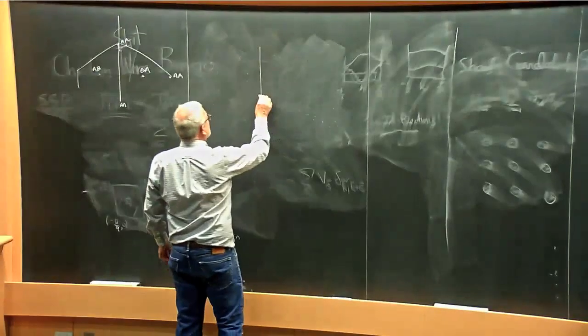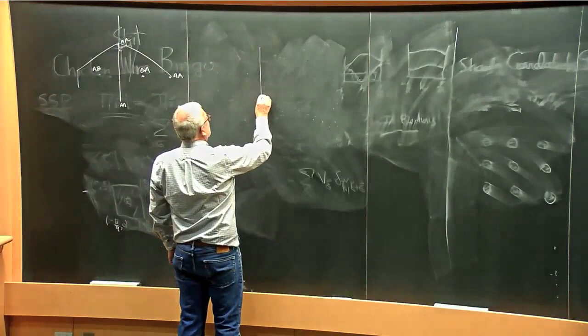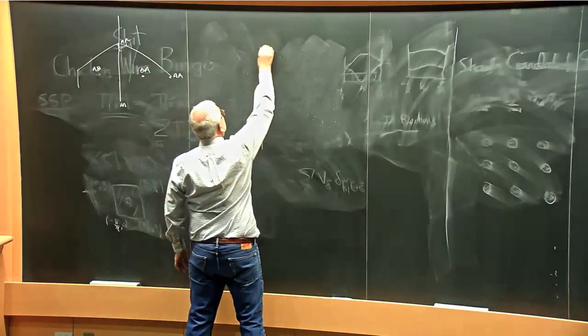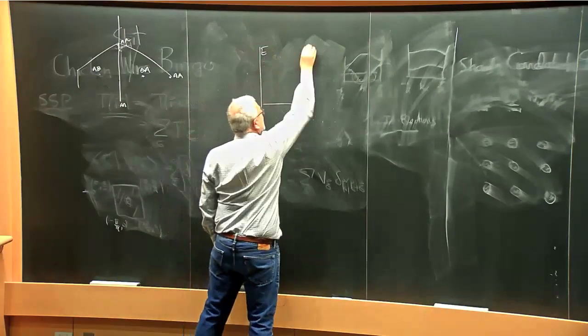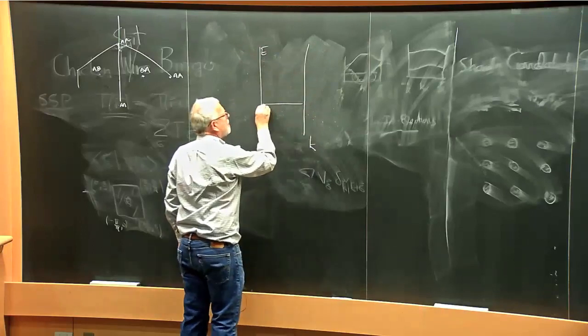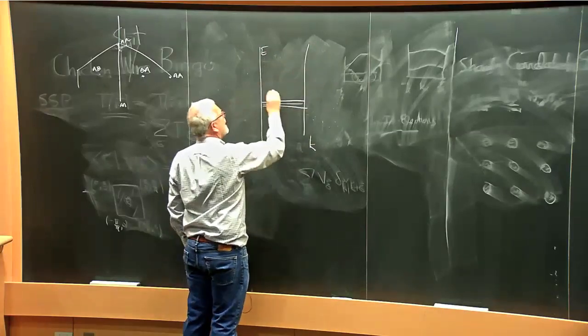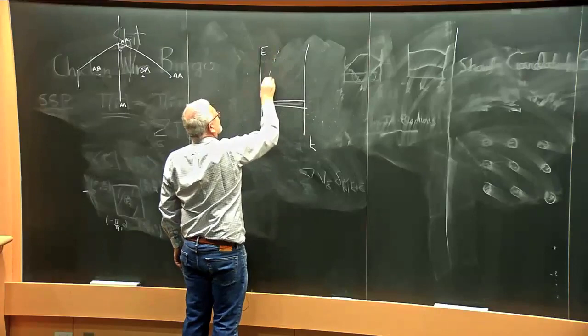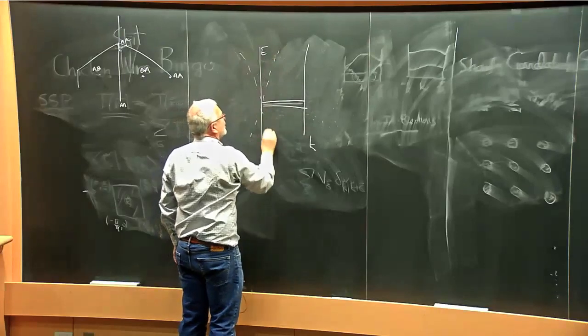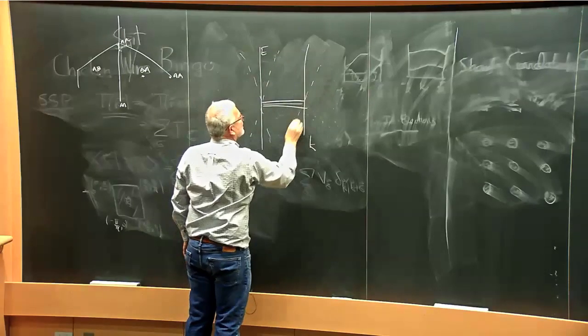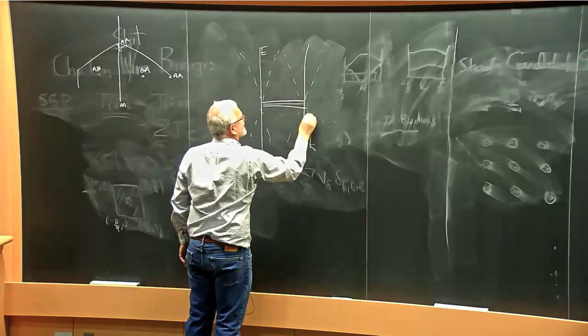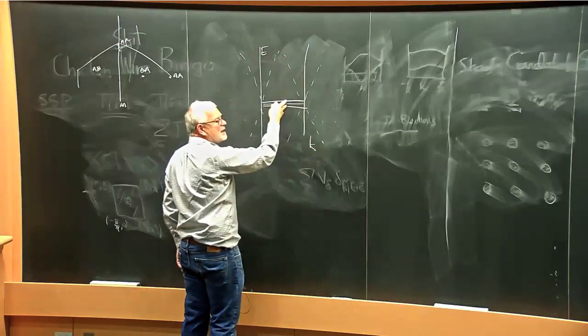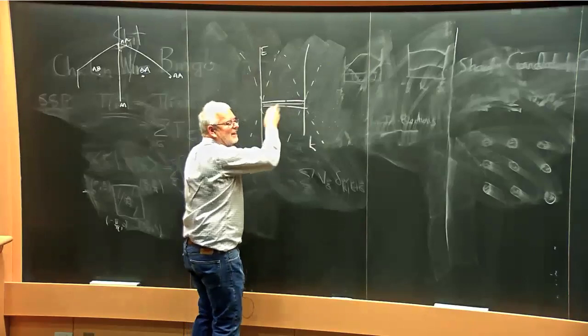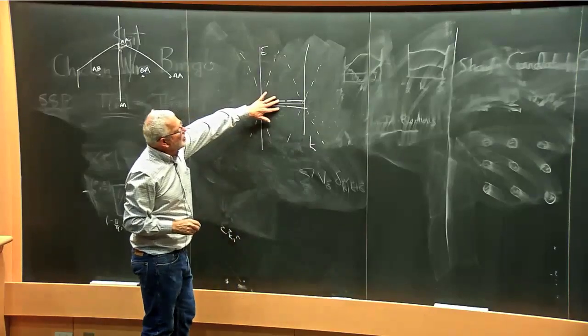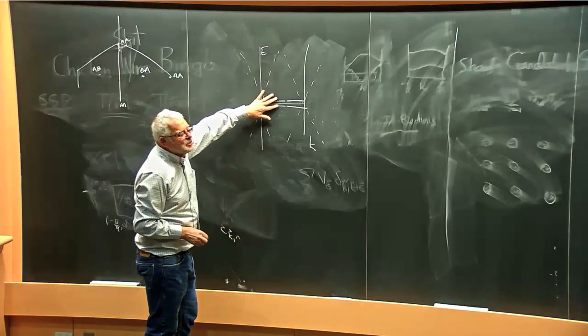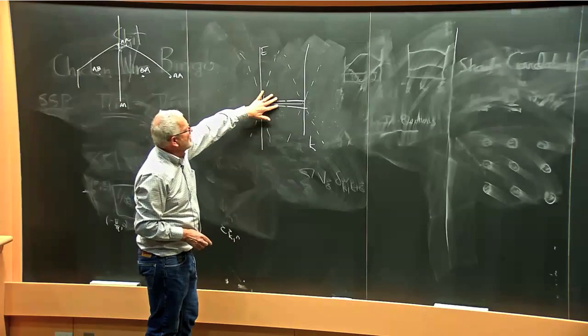And it turns out in that case, the lowest energy bands of what were initially linearly crossing Dirac bands at slightly different momentum become absolutely flat, nearly absolutely flat. That means strong correlations, as I said at the beginning of the talk.